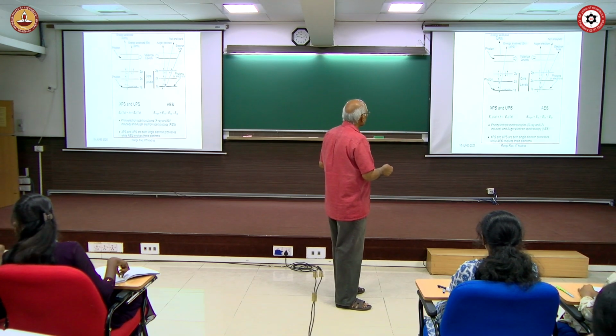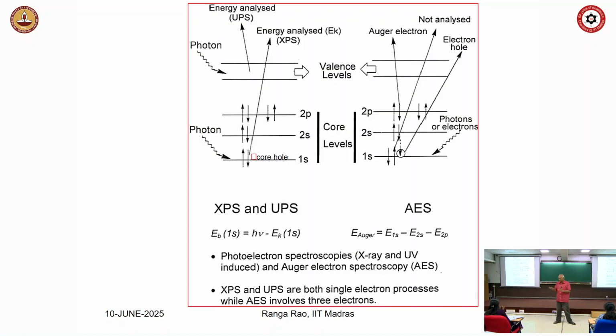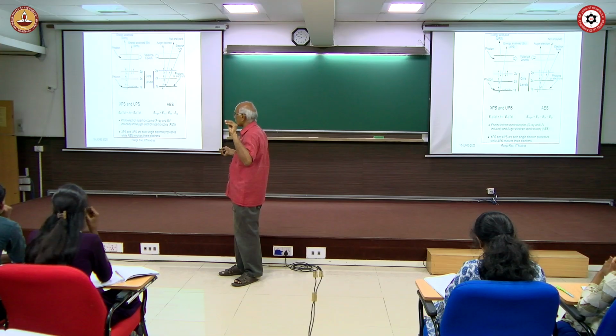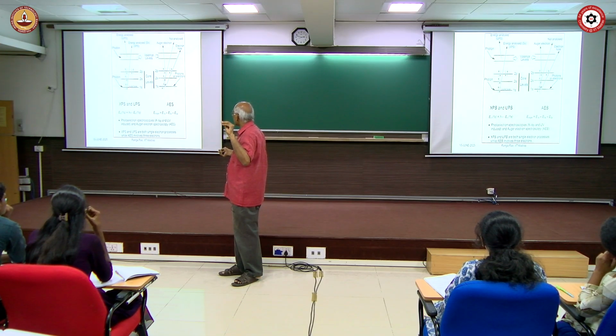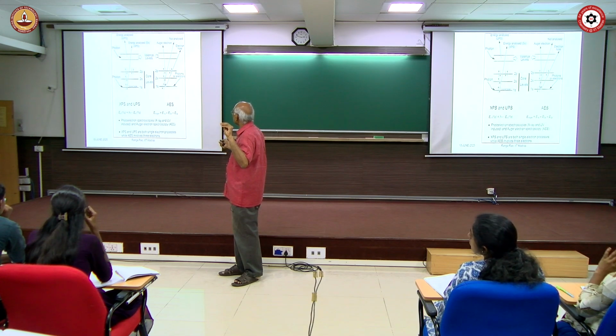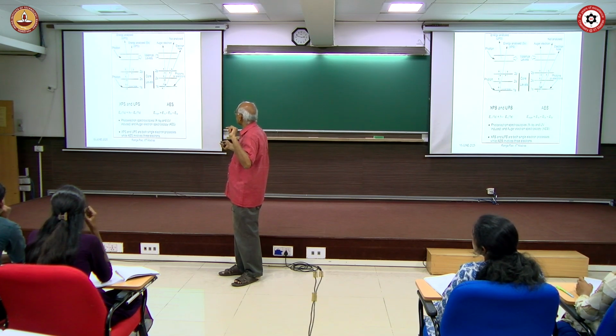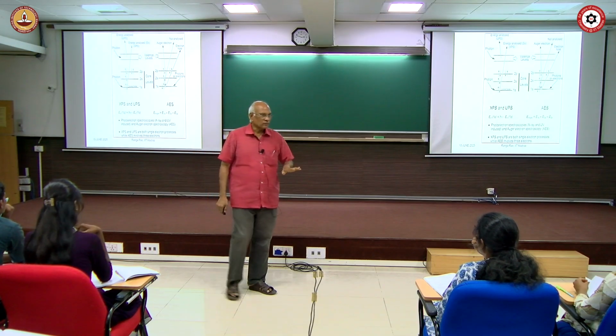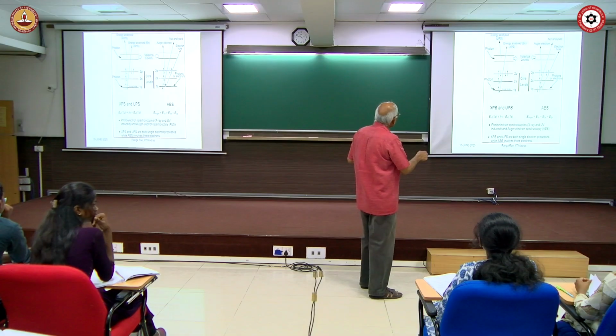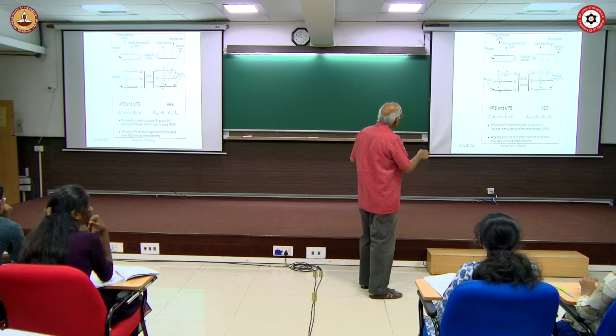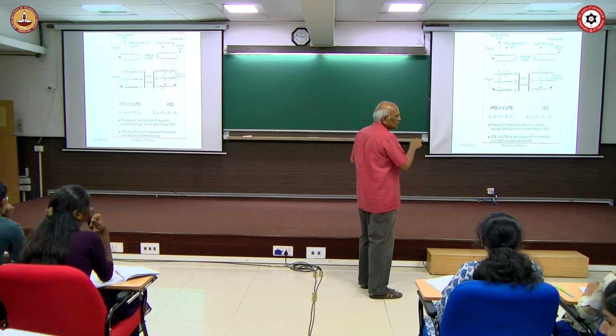Okay, so this is the summary of what I was talking about. You have these levels: 1s, 2s, 2p, and so on. When you go up, you have a band or valence levels. Now you remove a core electron using a photon. This photon should be an X-ray photon. You remove the electron from here, this electron comes out, you analyze the energy of this electron which is coming out, and that gives you XPS. Whereas if you see electrons coming out from the valence levels or a valence band, then what you get is UPS.